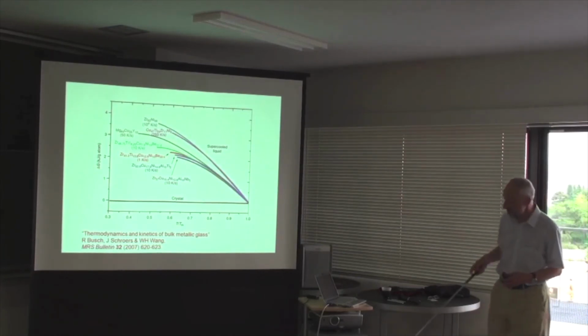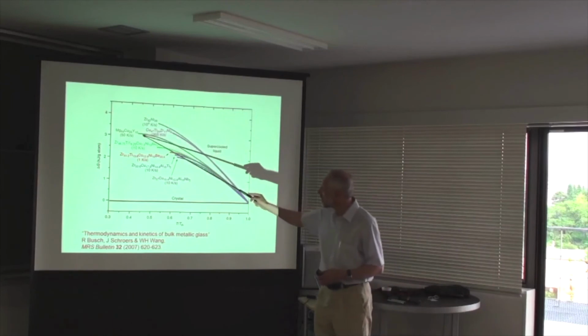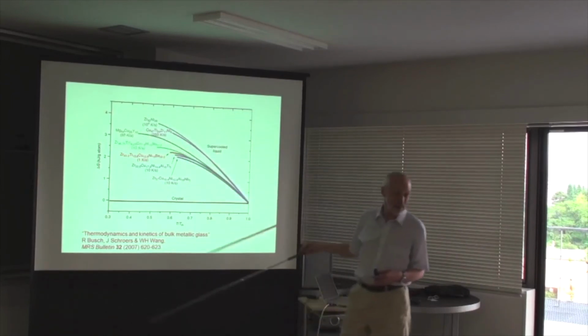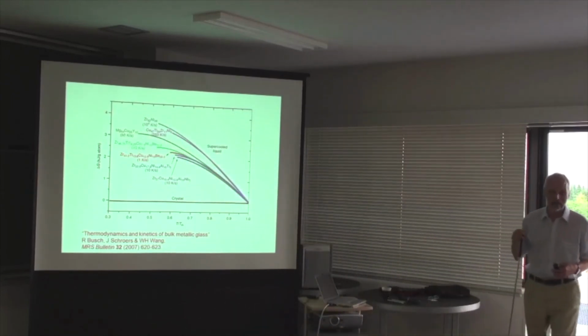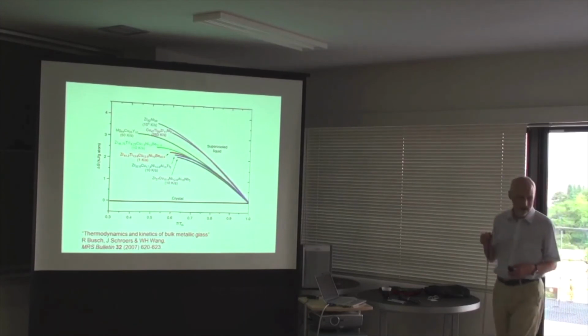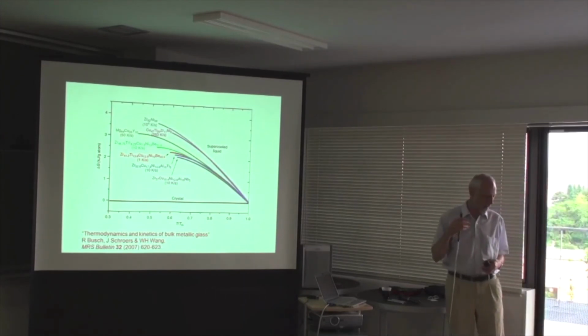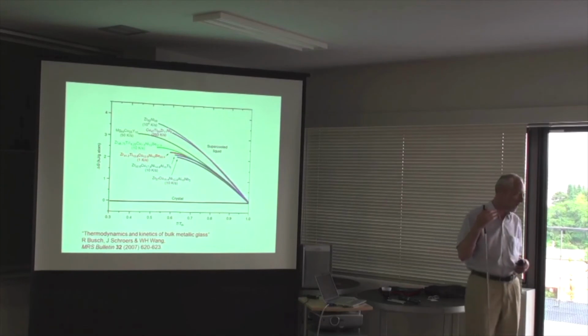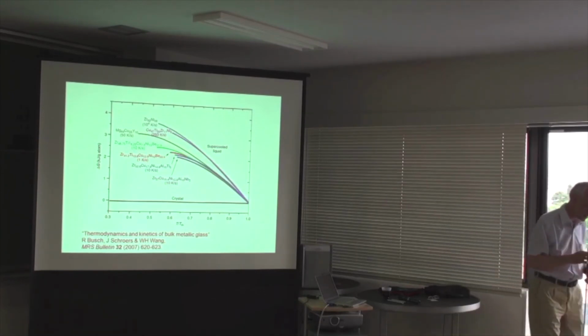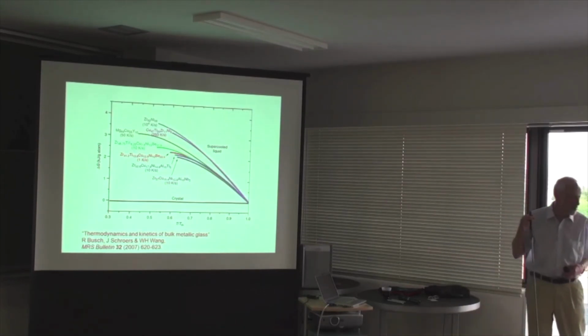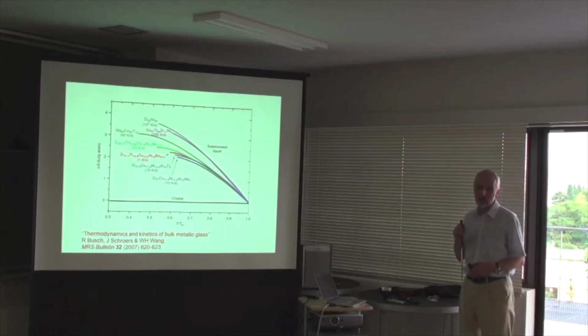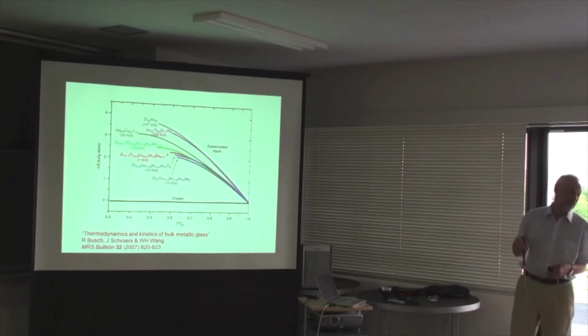Indeed, you can even get some examples where this curve curves downwards, which says the glass has even lower entropy than the crystal. And that would be very interesting for the AIMR to tackle with its MathMate program, and thinking about how does one even think about entropy in a system like this that appears to be so disordered but actually isn't.